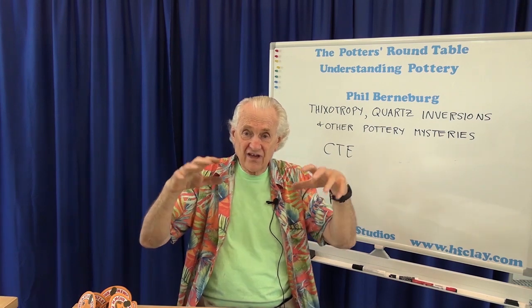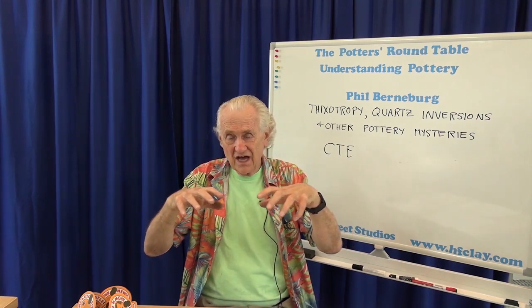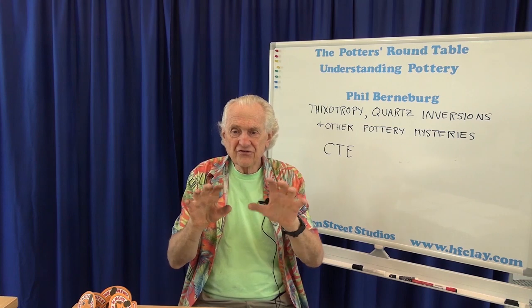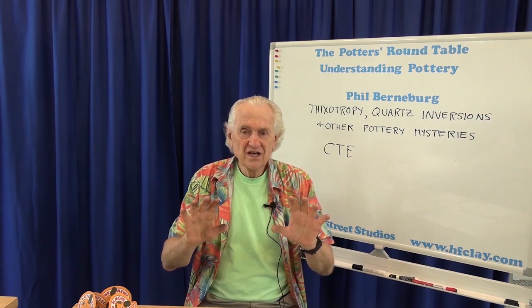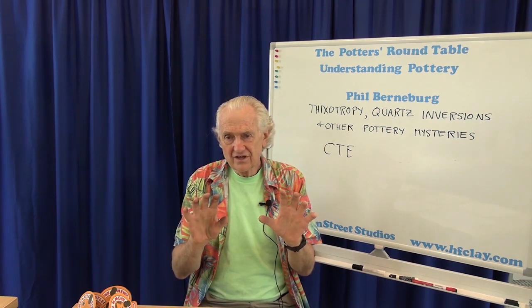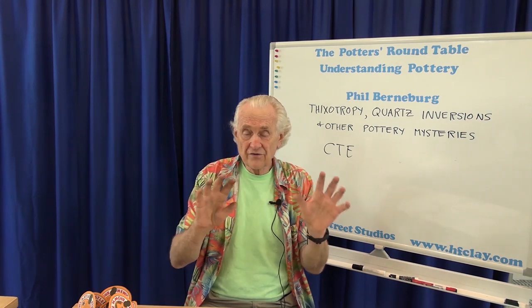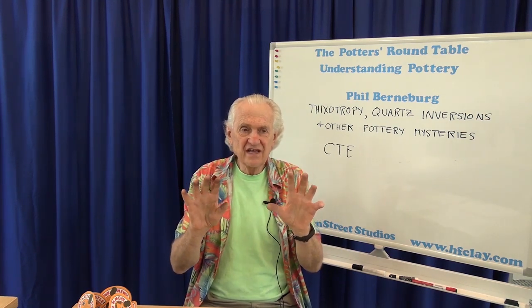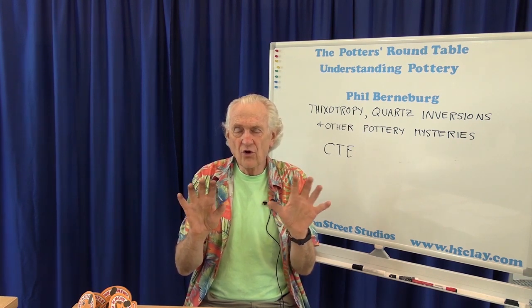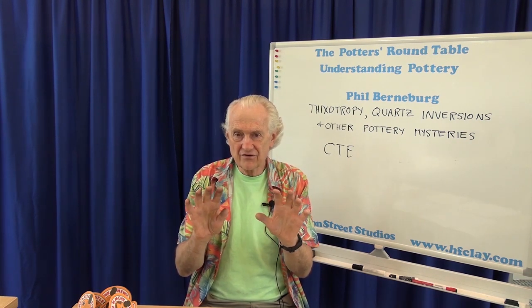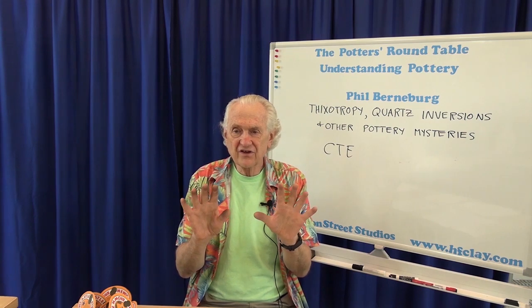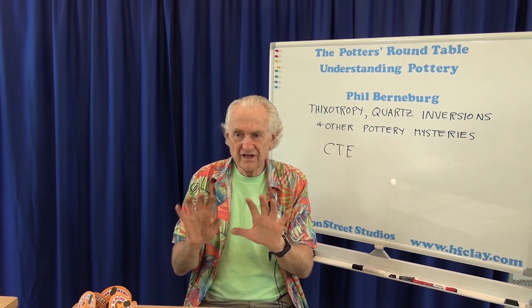So I have a layer of solid hot glass sitting on hot clay, and they're both trying to shrink as they're cooling down, but they're shrinking at different rates because the clay and the glaze have different coefficients of expansion. Well, if the glaze tries to shrink a lot more than the clay, all it can do is crack, and that's the crazing. So crazing is caused when the glaze wants to shrink more than the clay.